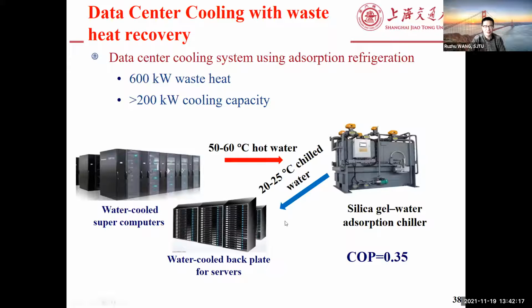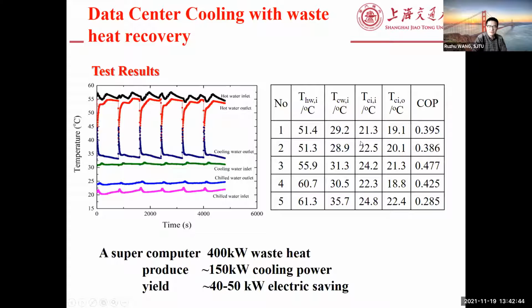And now I'm proposing this kind of system could be possible using about 60 degree hot water to power an adsorption chiller to get about 20 degrees chilled water with a COP of 0.35. So this could be used for the data center, because now it's water cooled, and usually the waste heat originally comes as hot water, so it comes to the cooling water power. Now it comes to the adsorption chiller. So we made a test powered with about 50 to 60 degree hot water, and this just shows the COP values. And we get the cooling water about 20 to 24 degrees centigrade.